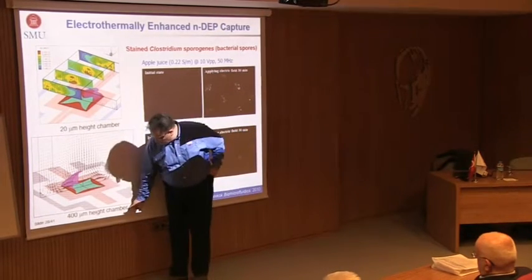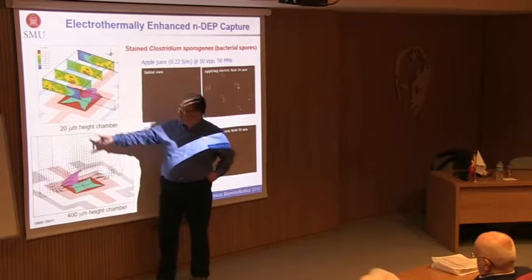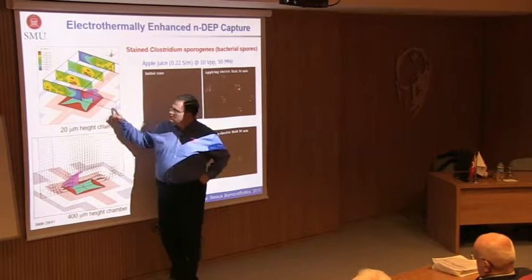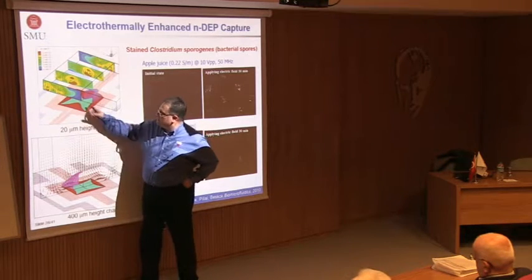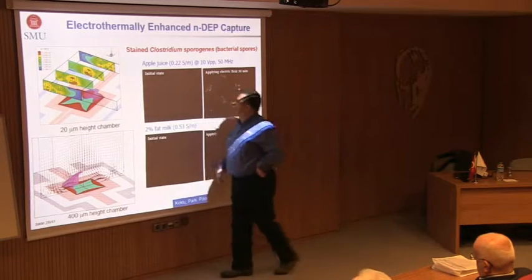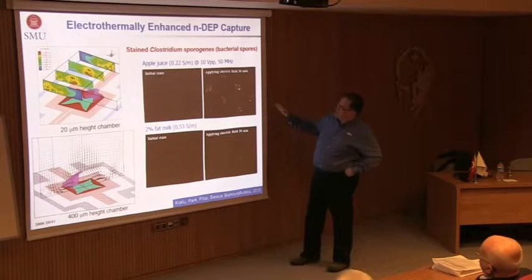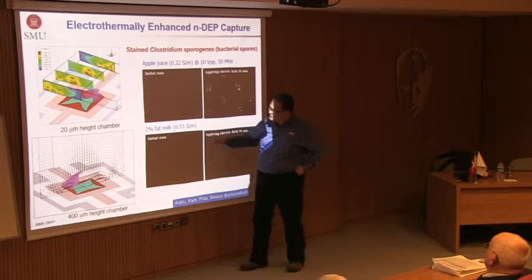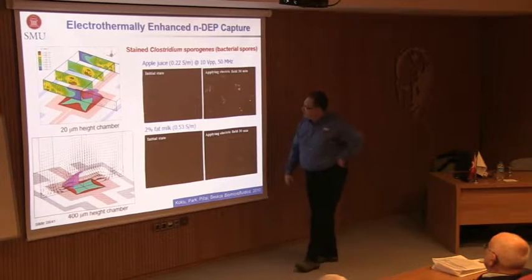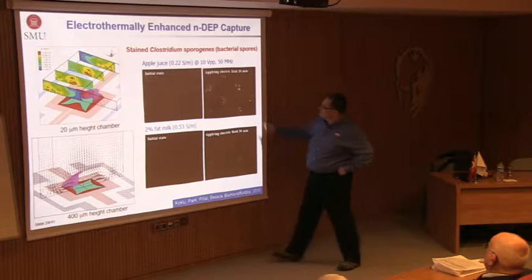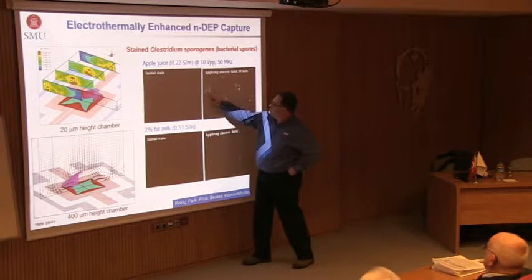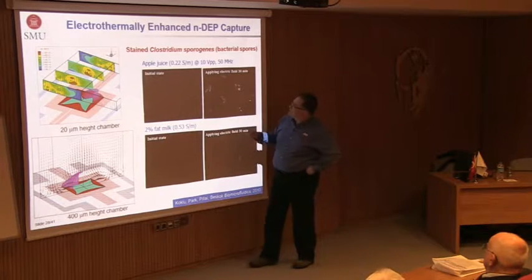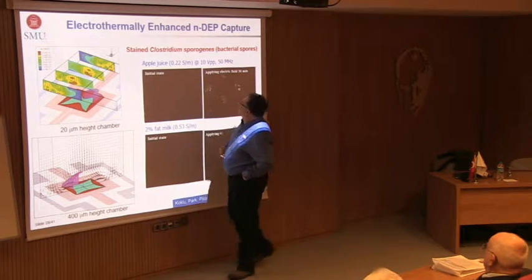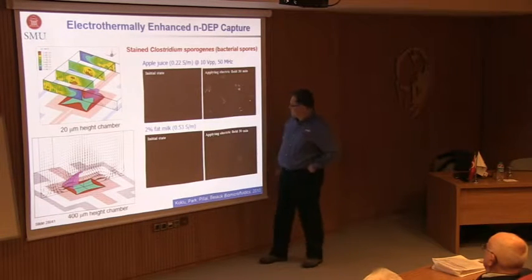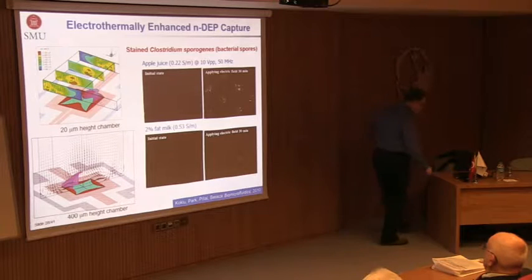Or you can actually totally ignore this and create only a 20 micron height chamber, and then, of course, the circulating loops and so on are not very important, and this may or may not work. So what we did was we used apple juice and we used 2% fat milk, and these are the conductivities here, and applying for 30 minutes in these square electrodes, which is hard to see in this, but these are our square electrodes. Hopefully you realize that we were able to concentrate Clostridium sporogenes bacterial spores in these electric field minima. And that was our work for food and beverage safety.